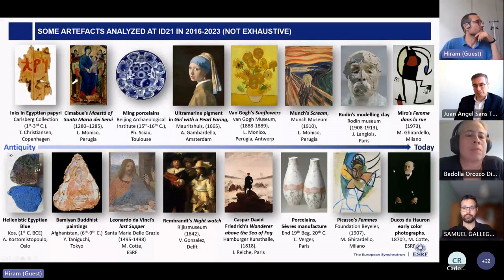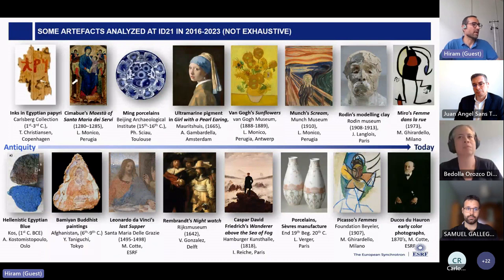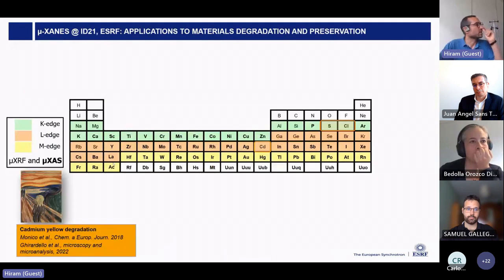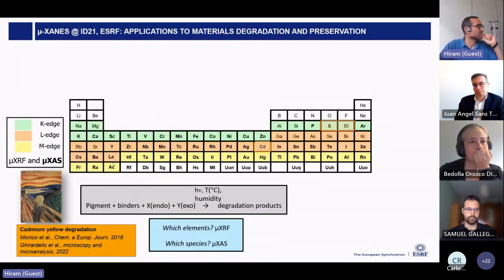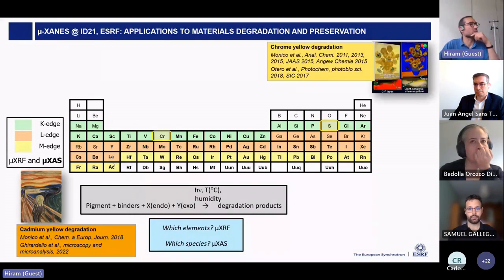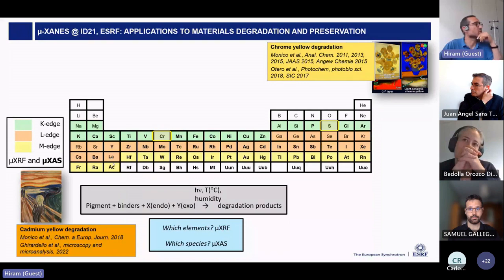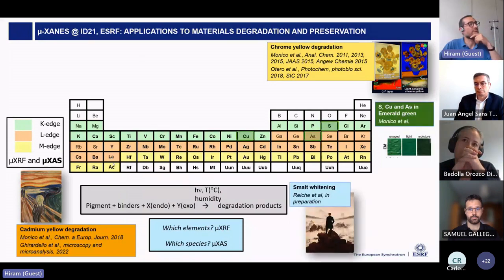And in all these objects that have been studied at the beamline, always the combination of X-ray fluorescence and X-ray absorption spectroscopy has provided important information to understand how they were done and where they are going and why they are degrading. So in here, I have just used the periodic table for many more examples. For example, cadmium yellow degradation in the Scream painting. So typically you have a pigment which is embedded in some kind of binder, and you have exposure to different environmental factors, and this leads to degradation of the products. So as I mentioned, the chrome yellow degradation in Van Gogh, but also the cadmium yellow degradation in the Scream, and other kinds of paintings.